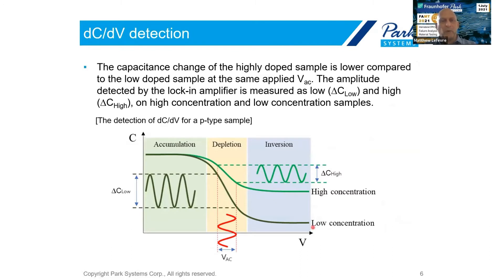The other thing you need to be aware of for SCM is that if we have a material which has both high and low doping concentrations, for high doping concentrations we actually get less of a capacitance change with voltage. We can imagine this by thinking that for a given voltage, if you have a higher concentration of doping, you get less depletion underneath the tip than you would with a low doping concentration. So we actually get higher signal and we're more sensitive to lower doping concentrations than higher doping concentrations in scanning capacitance.